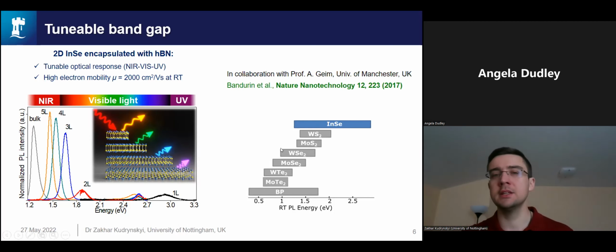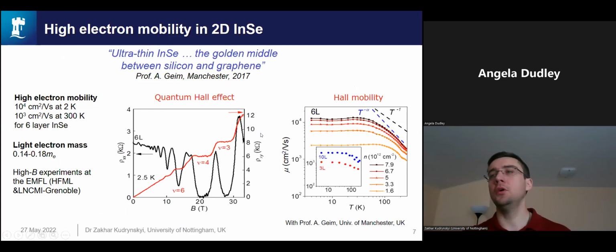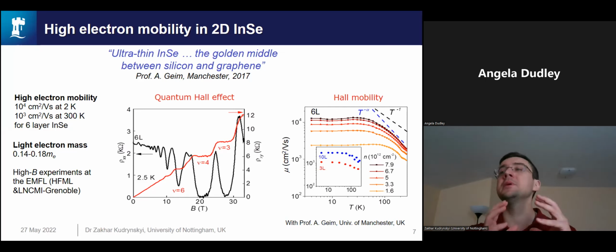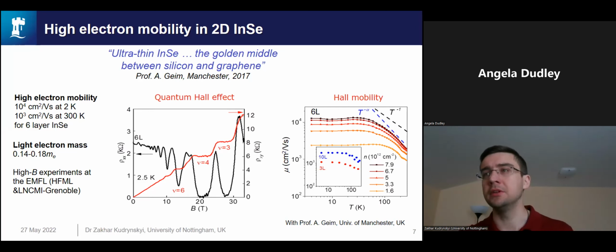So I have just shown you that it's an interesting material optically, but it also has a high electron mobility, higher than in silicon, and one of the highest within the family of 2D van der Waals crystals. And that manifests through the observation of the quantum Hall effect in very thin layers. This combination of 2 important properties, tunability of the bandgap and high electron mobility, is very important for a semiconductor, and led Andrew Geim to comment that ultra-thin indium selenide represents a golden middle between silicon and graphene. Since this early work, we learned more about this class of 2D materials. It was important to understand not only how the properties of indium selenide change as we go to thinner and thinner layers, but also to get a deeper insight why this happens.